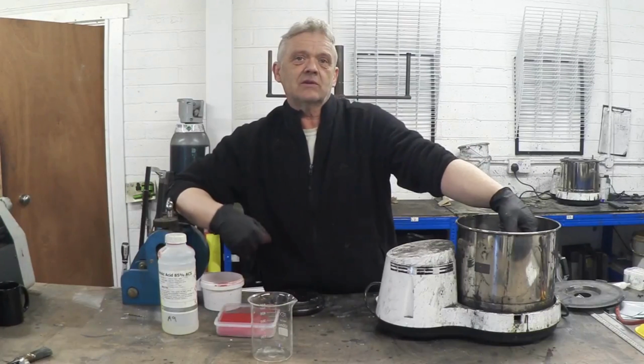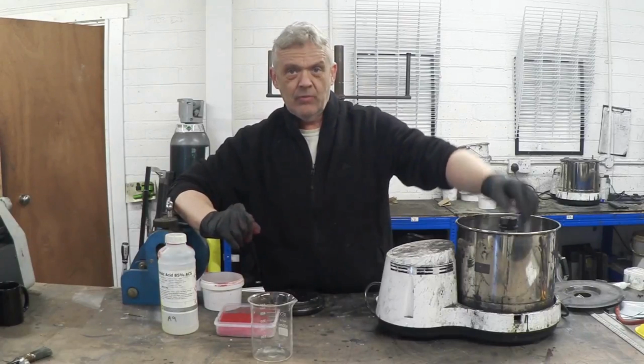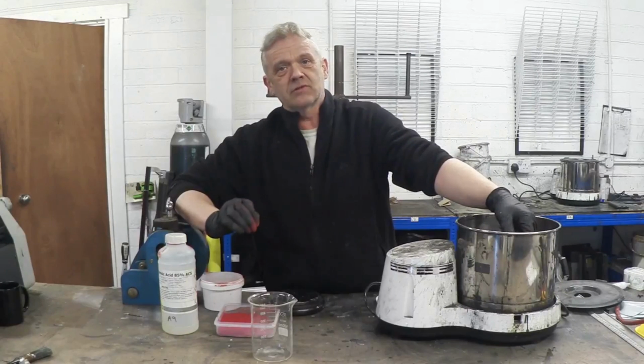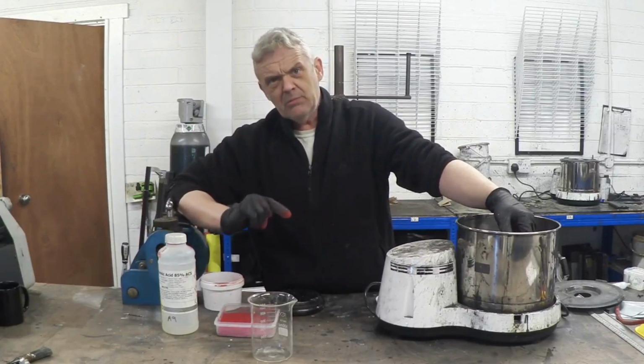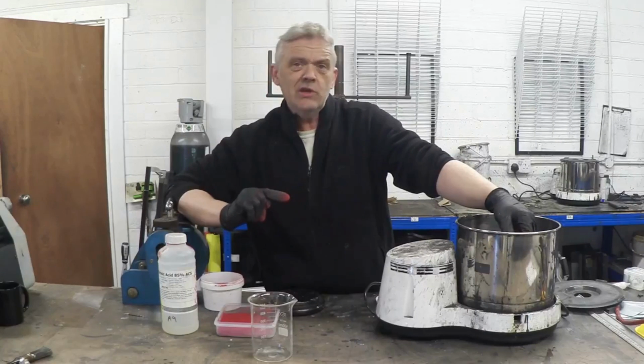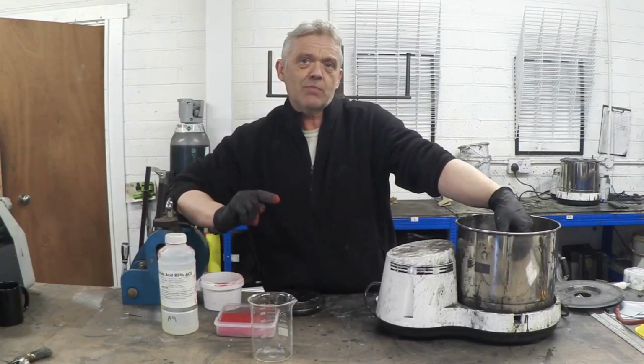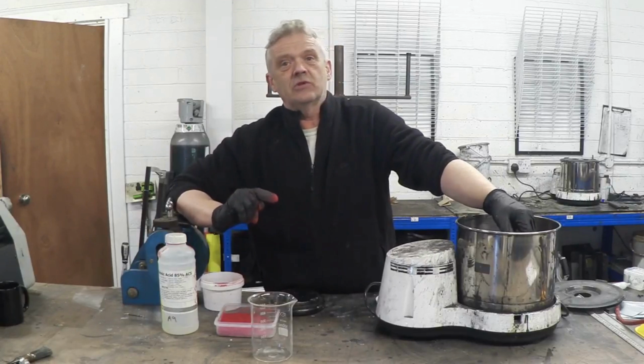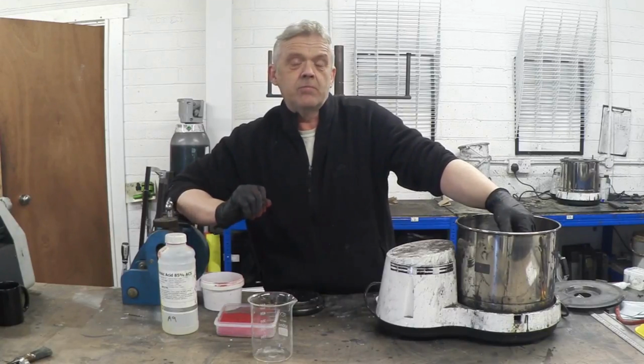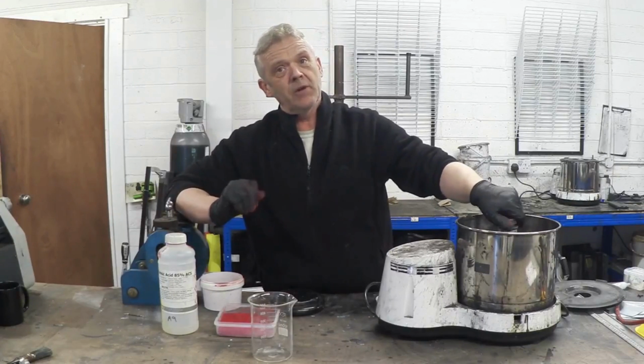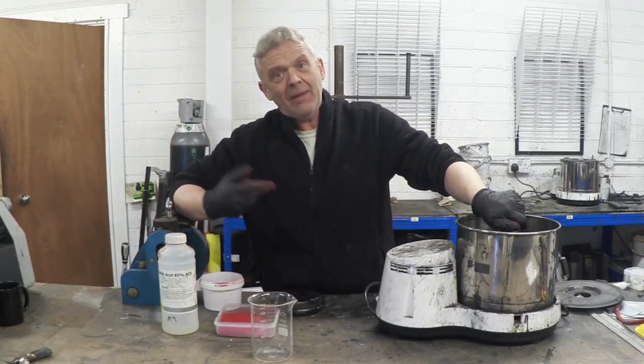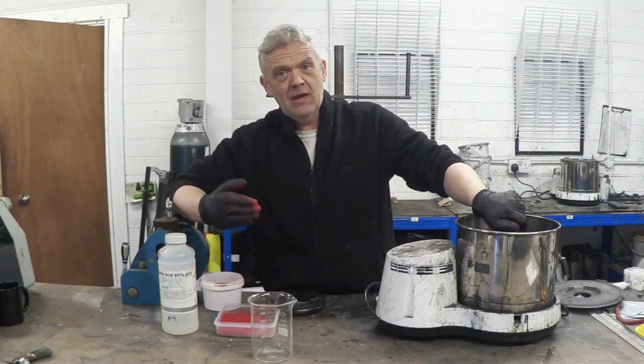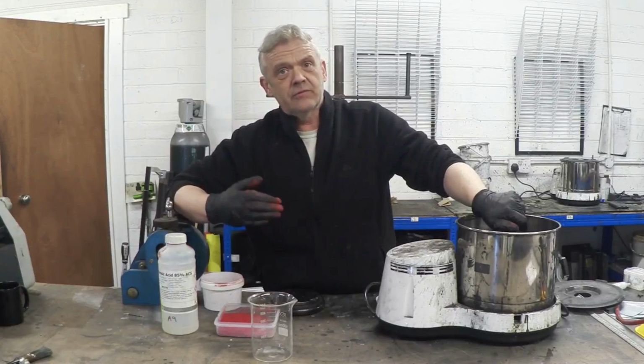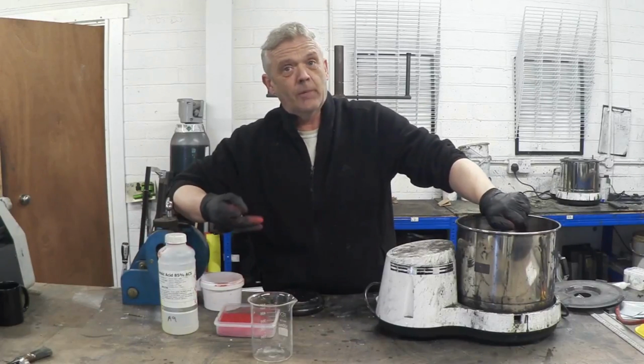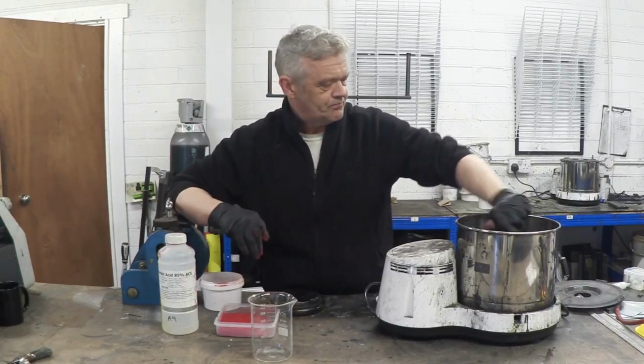Instead of making a few micrograms using wet synthesis, with this you can make absolute grams of that material. The resultant material that comes out of here is the stuff that we use to copperplate stainless steel just by rubbing it on the stainless steel. So it's an awesome material just for applying with a rag to copperplate surfaces in an adherent copper plate. That copper plate will happen with iron, but it's very flaky. With this and the nanoparticles in the formate, it adheres and gives a shiny copper plate. And I'll demonstrate that at the end of the video.